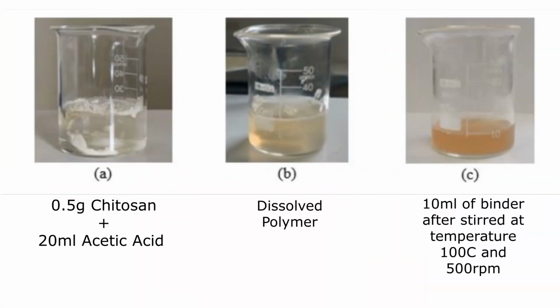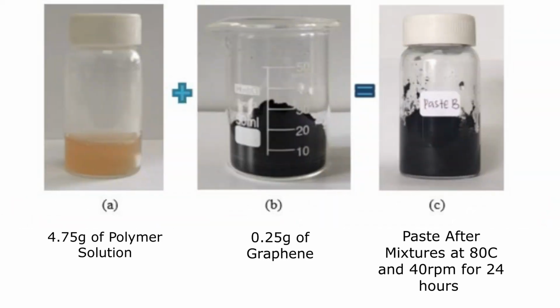Now, let's continue to the preparation of the graphene chitosan gas sensor. In preparation of the polymer solution, 0.5 gram of chitosan powder will be dissolved into 20 ml of acetic acid to become polymer solution. The solution will be heated and stirred at a temperature of 100 Celsius and 500 rpm for 3 hours. 4.75 gram of polymer solution will be mixed with 0.25 gram of graphene to become paste. The mixture will be stirred at 80 Celsius and 40 rpm for 24 hours.